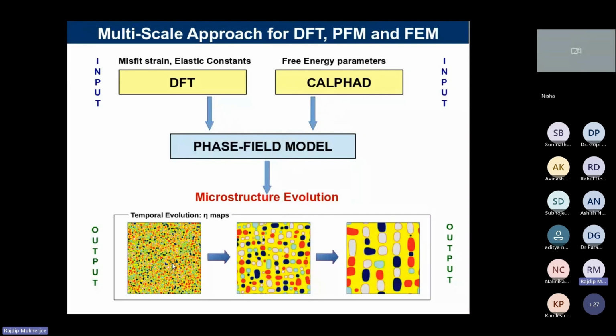Here you can see how the microstructure is evolving with time, right? It starts with very small precipitates having defined orientational variants, translational variants of gamma prime in a gamma matrix, right? So yellow is the gamma matrix and all other colors are gamma prime precipitates, but these are defined variants, right? And how they coarsen with time. Coarsening is a process where the larger particles grow at the expense of smaller particles. So this process is slightly detrimental for the property of a material. And there are many ways we can stop this coarsening behavior. So it is very important to understand the coarsening of precipitates in a matrix.